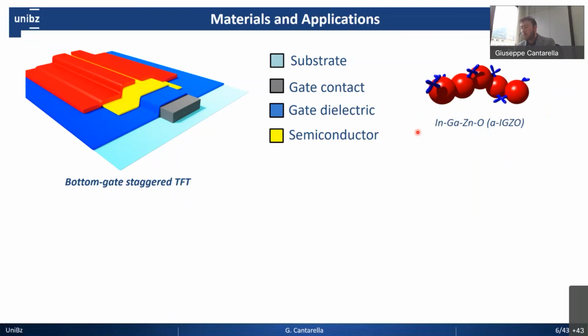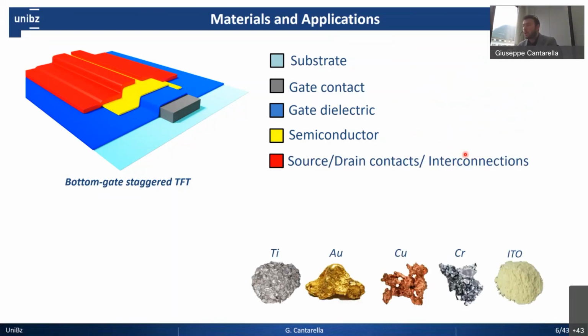As I was saying before, we employ one material from the metal oxide semiconductor family. In particular, we use an alloy of indium, gallium, zinc oxide at the amorphous state, sputtered at room temperature by radio frequency. And the idea is that this semiconductor guarantees an N-type functionality. So most of our electronics is NMOS only, and guarantees a mobility around 15 centimeters square per volt per second and threshold voltage below 1 volt. And then usually we conclude our fabrication with the source and drain metal contact or interconnection in case of circuits, again with a broad range of applications and a broad range of materials that we can employ.